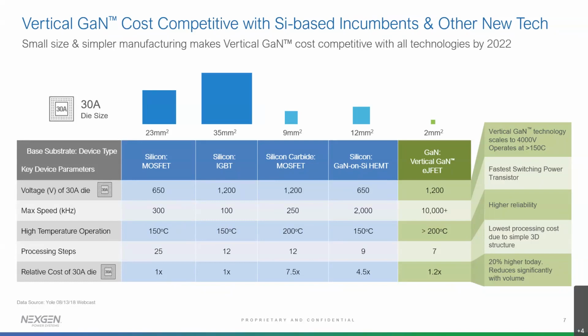Because we have the large band gap, comparable to and larger than silicon carbide, we can address the same temperature range, which is much higher than what we can do on silicon devices. And if you look at the commercial dimensions here, first of all, we have a simpler device with fewer processing steps. And because of the small die size, we can still maintain close to cost parity with the established silicon technologies, which you see in the comparison of the relative cost for the 30 amp die, and we believe that we can achieve cost parity in the next year or so.